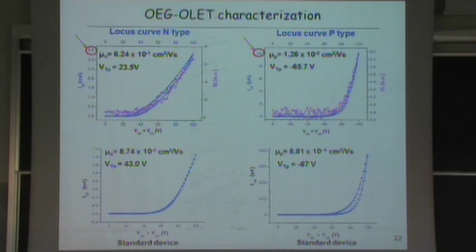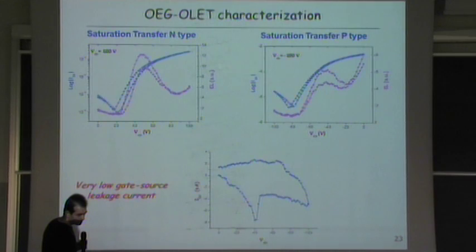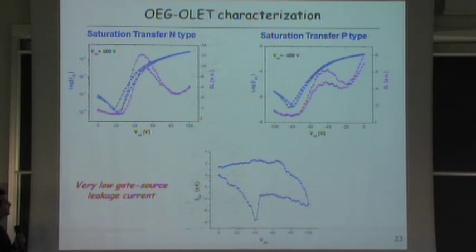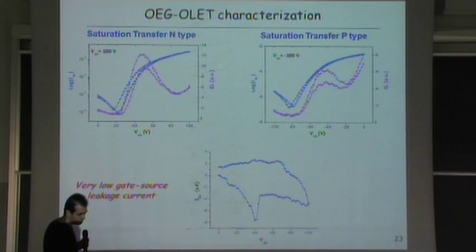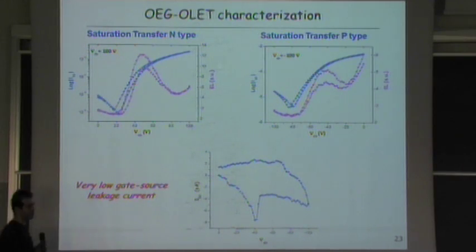Here the electrical characterization, where you can see the locus curve, N-type and P-type. You can see that the current is much higher in comparison to the standard devices. So we are happy, it's a good result. Also here we took out the saturation transfer curve, P-type and N-type, to verify the ambipolarity of this material. But here it's important to note the low gate source leakage current. It's very, very low. So I think the device will work also without PMMA buffer layer.